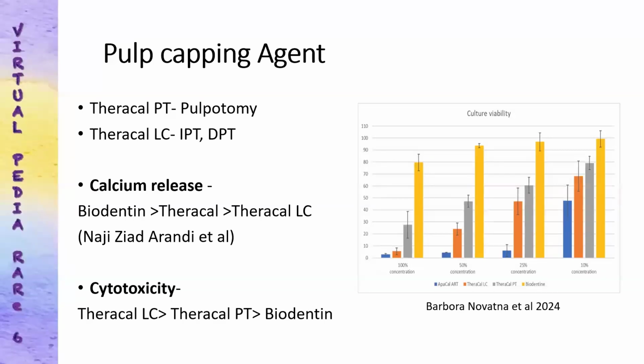So when we compare the pulp capping agent for the DPC or maturogenesis or revascularization, TheraCal PT is a new resin-based material which can be used for pulpotomy and DPC, whereas TheraCal LC is used for IPC and DPC. When we study about the calcium release of all these materials, biodentine has got the highest amount of calcium release, followed by TheraCal PT and TheraCal LC. The cytotoxicity of TheraCal LC is more than TheraCal PT and biodentine. So biodentine is the best material for revascularization and maturogenesis.